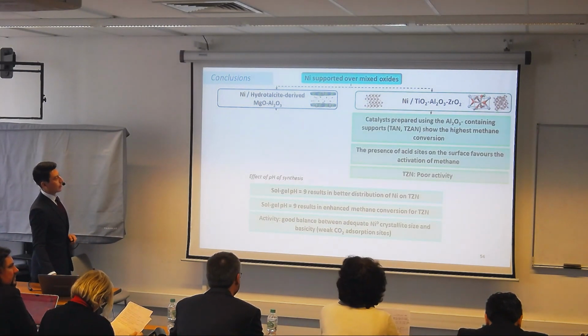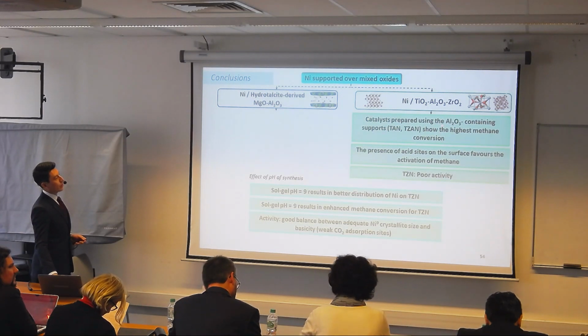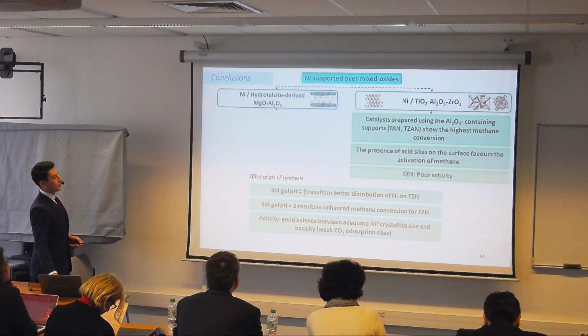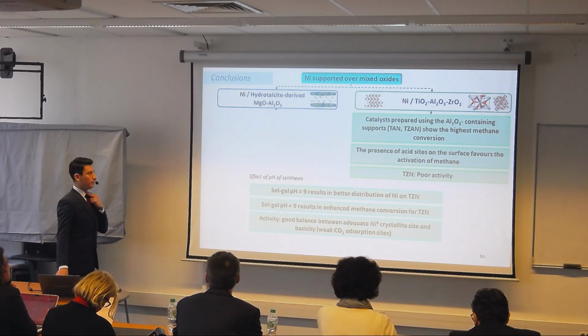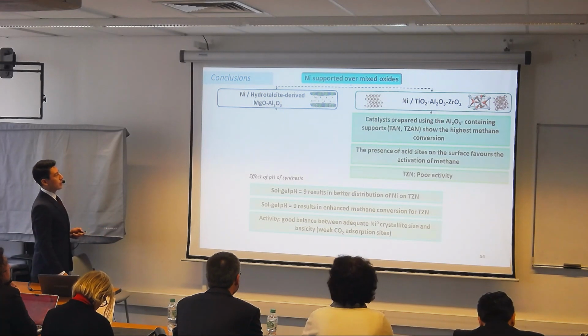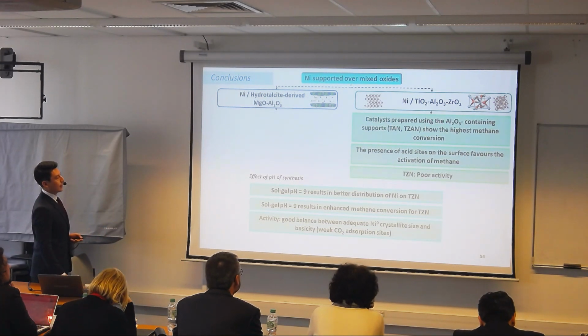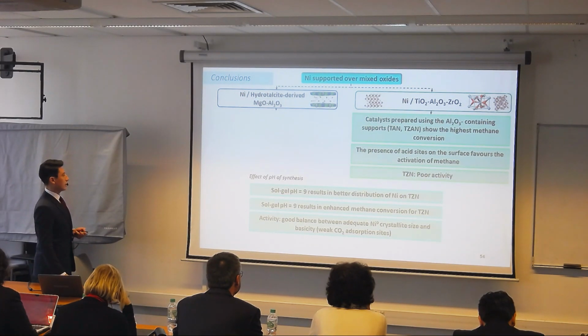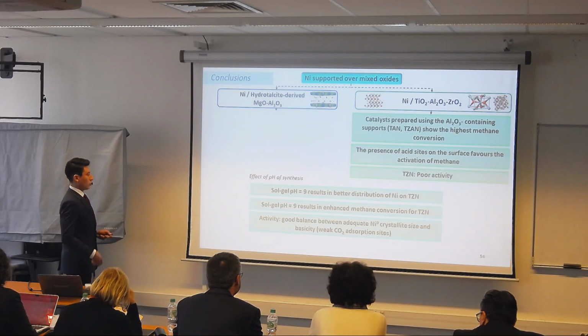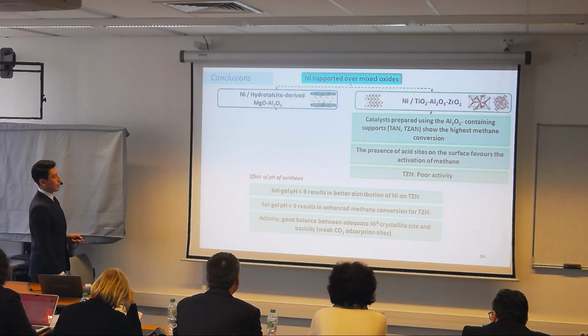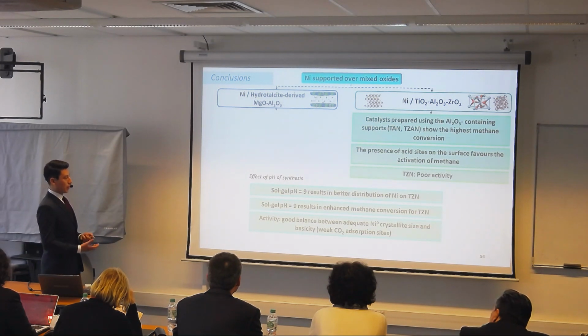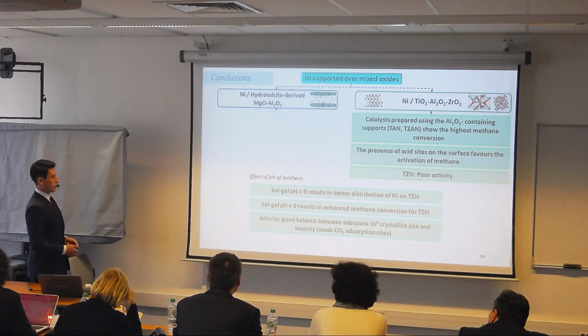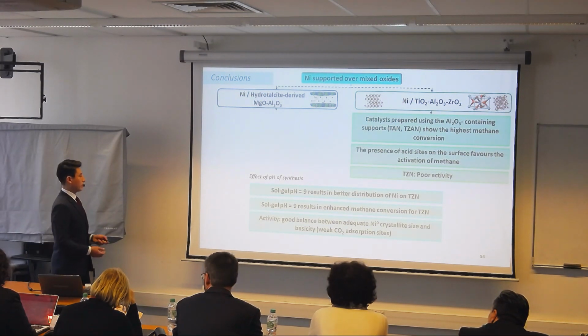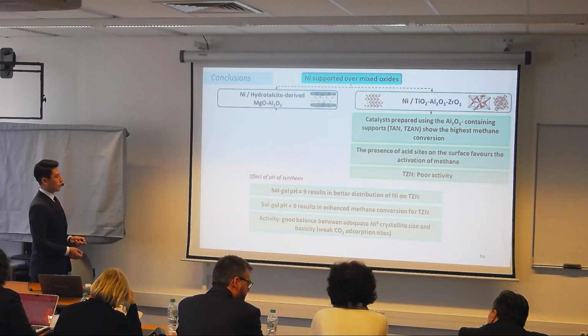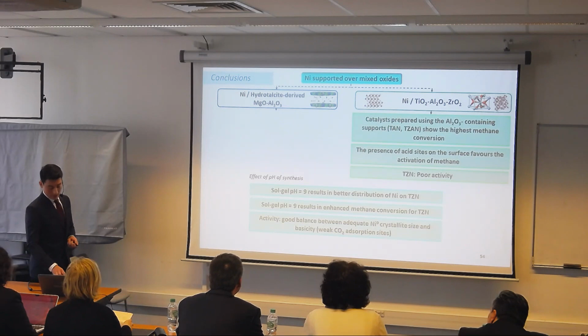Talking about the other group of catalysts, mainly we can say that the catalysts containing alumina show the biggest conversion. This is due to the presence of acid sites that may favor the activation of methane. As we saw, the titania-zirconia catalyst is the one with poor activity, so we wanted to modify it by the pH in the synthesis. We saw that a pH of 9 results in better distribution of the nickel and also enhances the methane conversion. So the activity is mainly based on a good balance between the nickel crystal size and the basicity of the support.